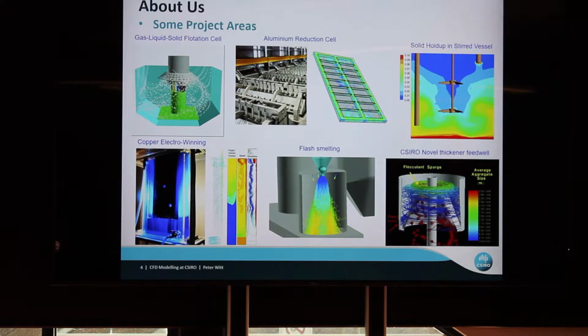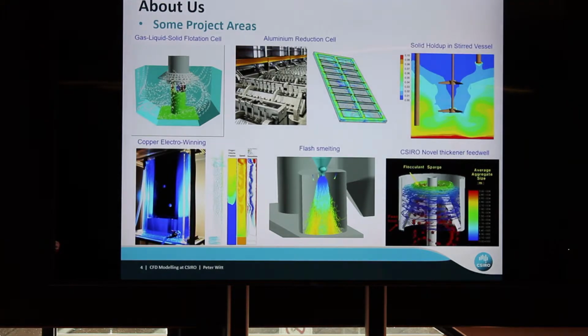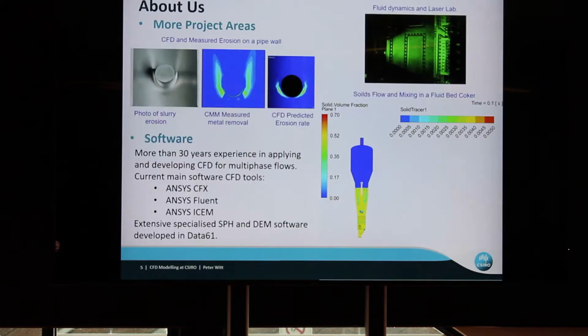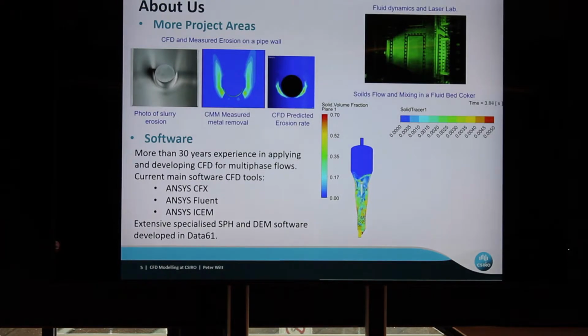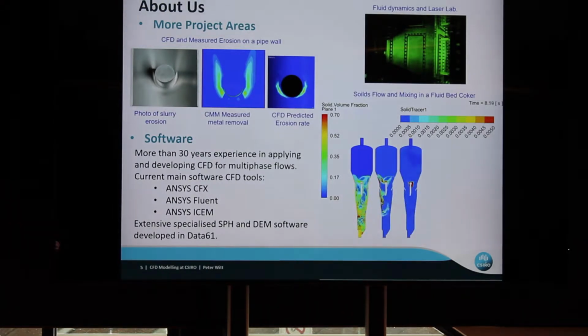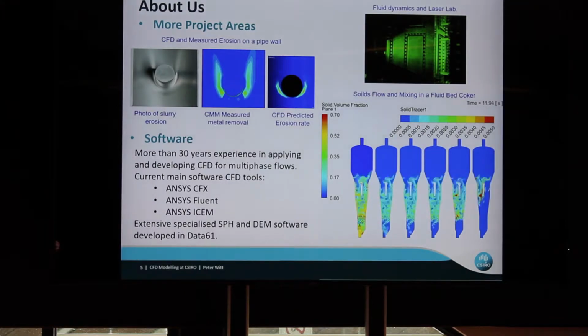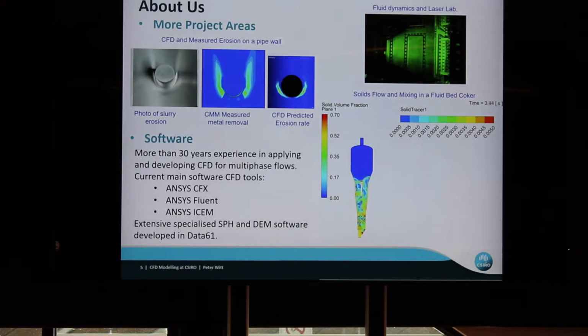Done work in electrowinning for copper and have quite a unique experimental system there, a full-scale single cell for generating something like 25 kilos of copper in a production run. Done work on flash smelters, and over 28 years of thickener development through Amira projects. We've done work in erosion, have experimental facilities where we can measure the erosion using a contact measurement machine to get the profile and the depth, and then we can reduce that in CFD modelling and link that into a lot of slurry and gas particle systems.